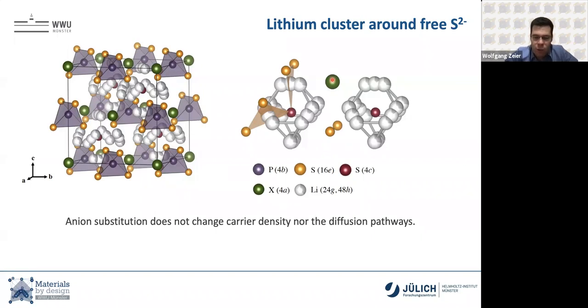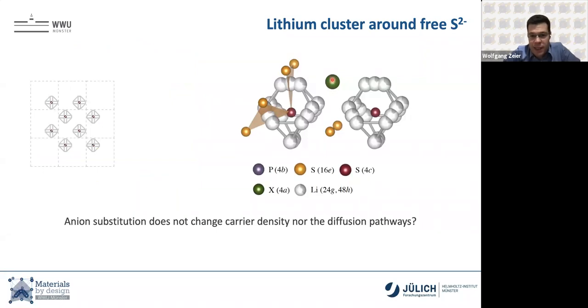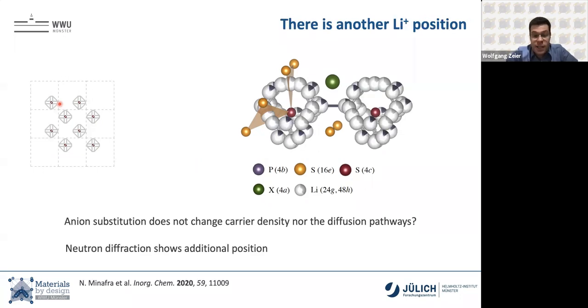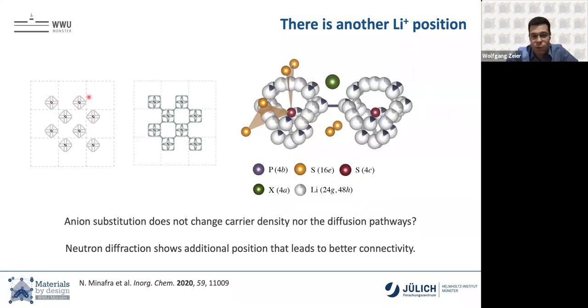Now, when we do a topological analysis of these lithium sites, projected into 2D, you see that these cages are actually fairly isolated. It's a long jump. It's too long for it to be happening. Yet these materials are some of the best ionic conductors for lithium that we have out there. Why is that the case? Well, it seems that this lithium substructure is incorrect. We actually found an additional lithium substructure that makes this cage seem a little bit more clustered. And what it really does is connect these formerly unconnected clusters or cages to each other. So we do have really good connectivity in there in certain compositions.